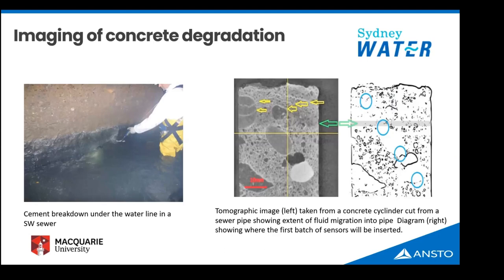We've been working with Sydney Water specimens through Macquarie University. The sensitivity to hydrogen means we can take drill cores from sewers and look at the effect of acid attack on concrete — the depletion of concrete and increase in hydrogen or acid concentration with depth. A cross section through a neutron CT scan shows yellow arrows highlighting layers of enriched hydrogen within the concrete, and green highlighting where depletion of calcium has occurred, supporting XRD and other measurements in three dimensions.